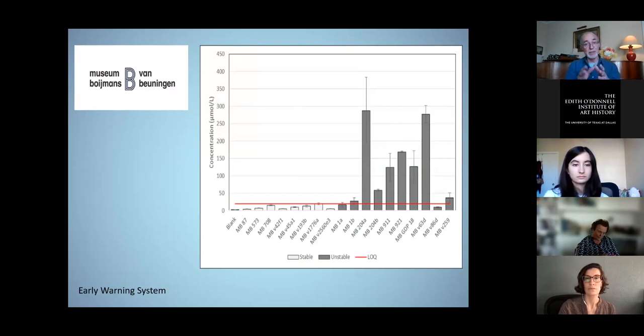have been leached out, have been swabbed off, have been analyzed, and we see that all those solid bar charts to the right have high levels, tall columns. All the objects on the left, less so. And it's very satisfying that the designation by conservators of stable or unstable fits precisely with the amount of materials that are obtained. And we're refining this process